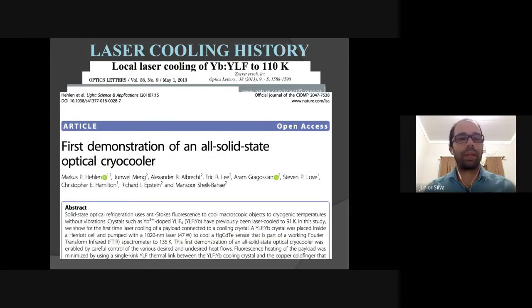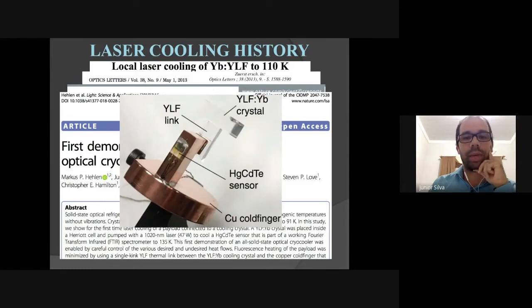And in 2018, this material was used for the first time in a real situation to cool a sensor. And we can see the setup here. We can see the cold finger, the sensor that was used. It's a sensor used in a very well-known Fourier Transform Infrared spectrometer. And the sensor was cooled to 135 Kelvin. And you can see there the crystal being used for this refrigeration situation.